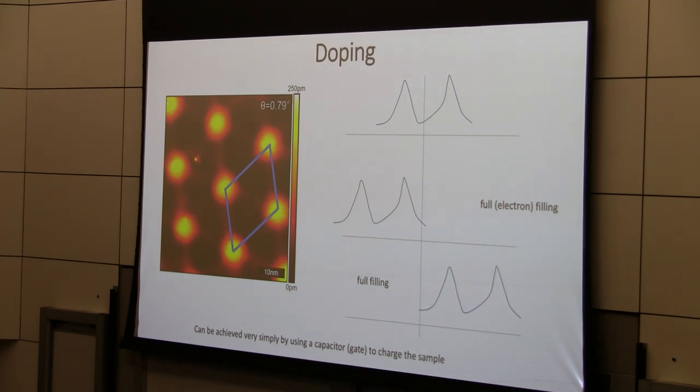And that, to my mind, is really one of the key advantages of these kinds of materials as modern quantum systems. Normally, when you want to do this with a three-dimensional material, your only choice really is to change a parameter like doping. And doping always brings with it chemical inhomogeneity and all of these things. So you're really studying different samples. This and this are different samples. Here, by just applying this gate voltage, you can study all of these samples in just one experiment.